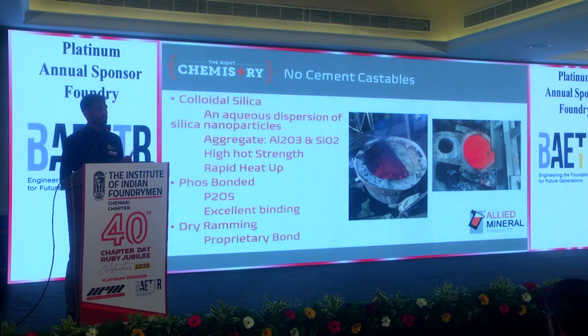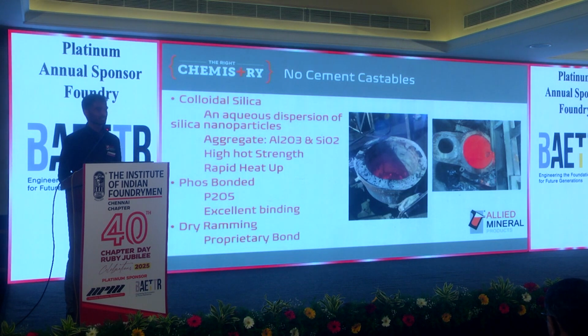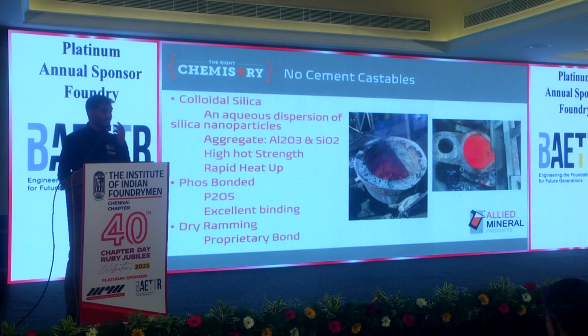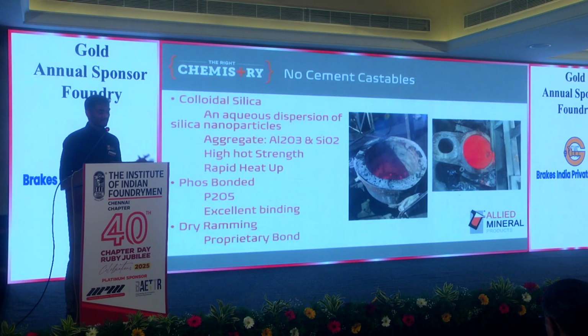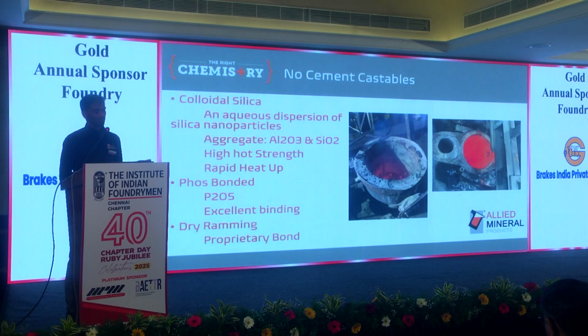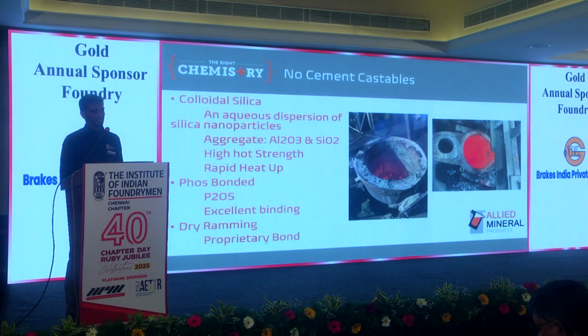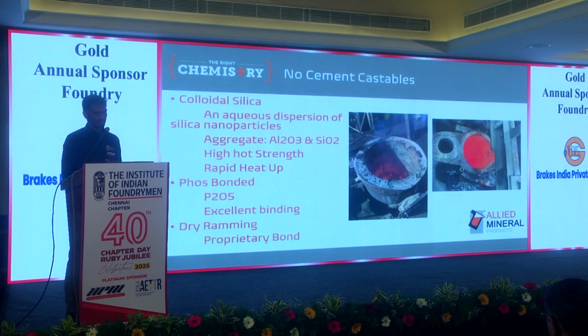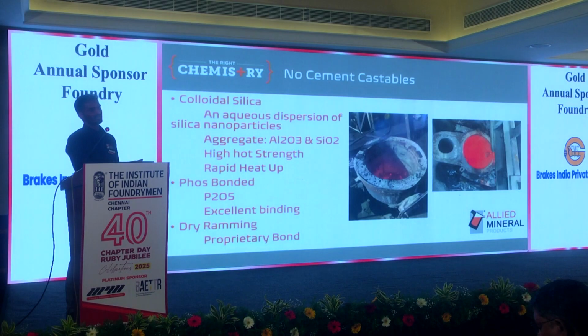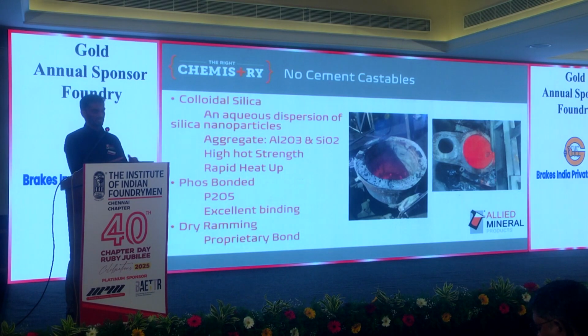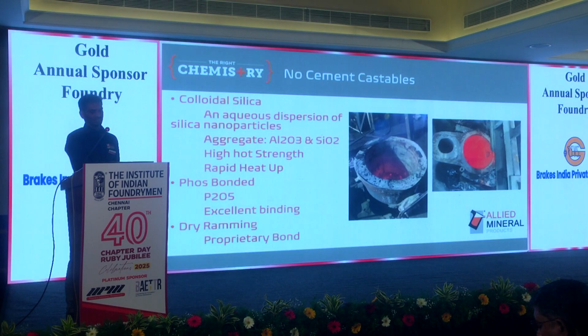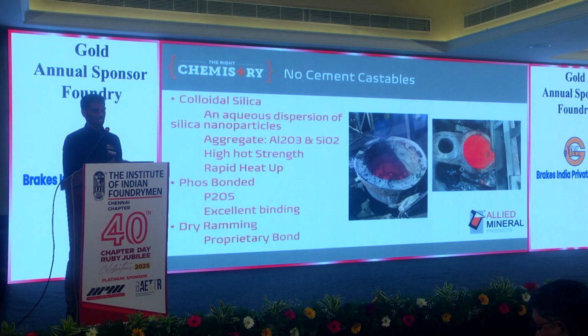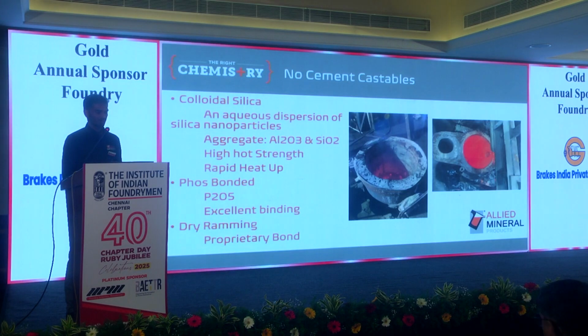You'll get a higher hot strength compared to any cement based castables, as I said earlier, because cement weakens the structure also. But the only disadvantage is the green strength is way less. So we need to be careful in the initial stages. As soon as you line the ladle, rather than moving it to any other place, try to heat up the ladle on the same spot. So transportation has to be minimized as much as possible.